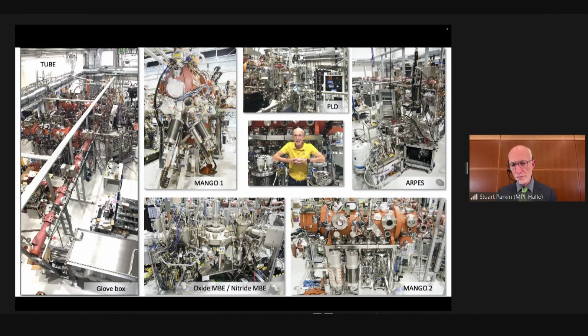But now we can transfer these wafers from between different ultra-high vacuum systems. In particular, one we call Mango. This is homemade, but it's a very sophisticated system in which we can have up to 44 different sources of materials to deposit different types of elements or compositions or compounds in this way at temperatures up to 900 degrees centigrade. And then we can take a wafer from Mango and we can place it into a molecular beam epitaxy system or into a pulsed laser deposition system. These are different techniques designed to deposit different types of materials with greater efficiency than otherwise would be possible.